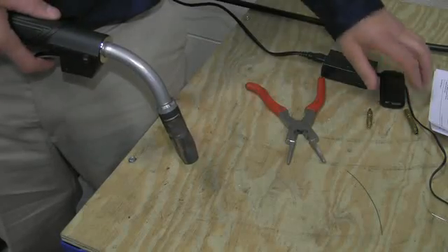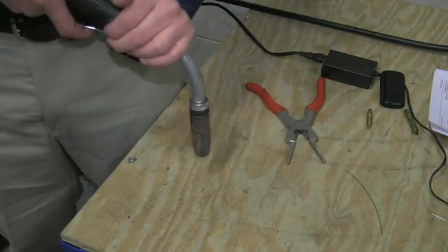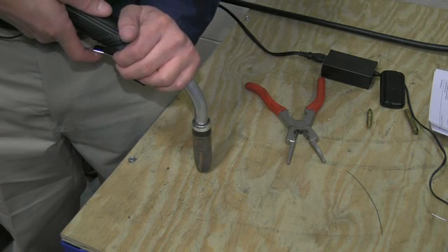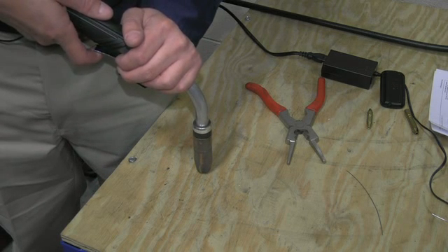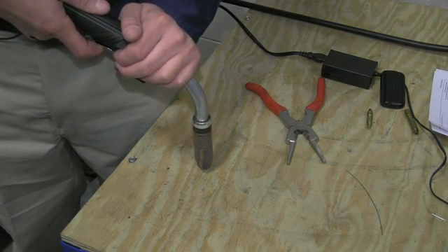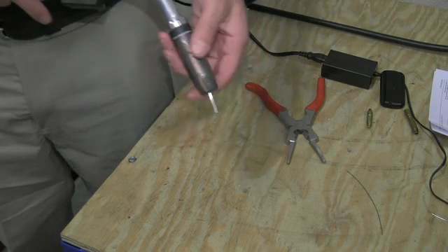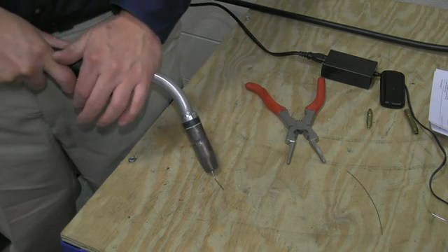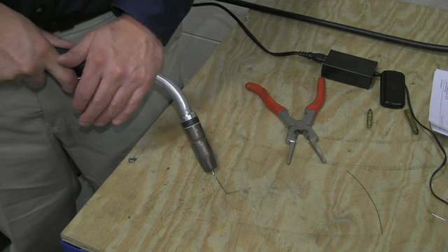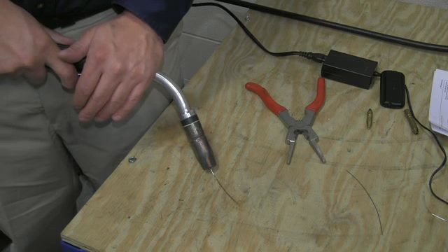Next, to ensure we didn't over-tighten it, you should be able to apply the MIG gun directly on the non-conductive surface, pull the trigger, and the wire drive should slip. And it is, and we're doing good. And just a double check, we'll put a bend in it, and then we'll feed it, and it's feeding without slipping.